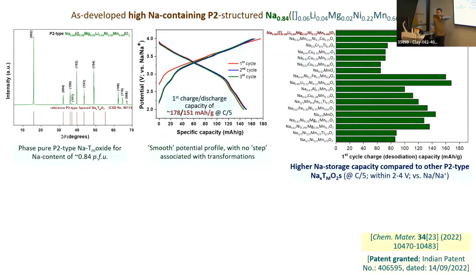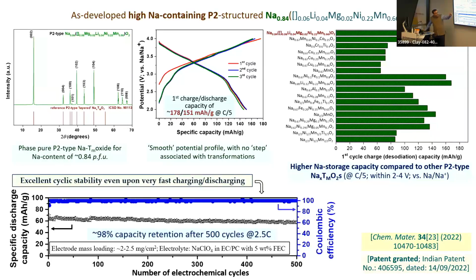it formed a perfect P2 type structure, phase pure, with a starting sodium content of 0.84, much better than the typical 0.67 per formula unit. And no doubt, it exhibited a very good first cycle reversible capacity, probably more than most other P2 structured materials reported in the literature. What I'm showing here today is between 2 to 4 volt. I'm not talking about what will happen if I go beyond 4 volt. And within the 2 to 4 volt, the cyclic stability was very good, even at a high current density of 2.5 C.